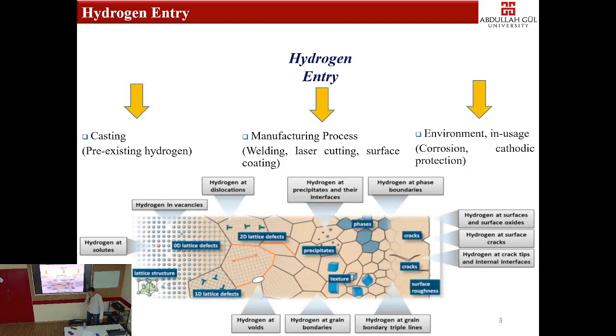Once hydrogen diffuses into the material, it can be localized at trap sites, or it can continue its motion, like diffusible hydrogen or trapped hydrogen. The trap sites are grain boundaries, phase boundaries, voids, inclusions. We have several trap sites for hydrogen, and mostly the interaction of hydrogen with defects is the main controlling mechanism of hydrogen embrittlement. So, diffusible hydrogen and its interactions with defects.